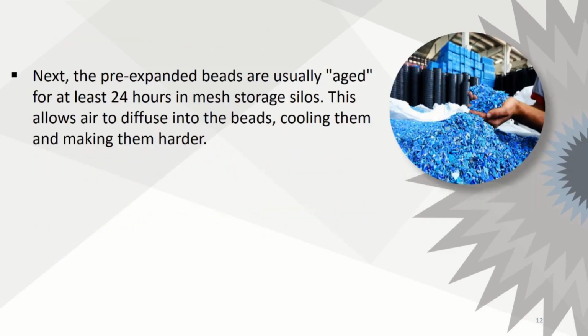Next, the pre-expanded beads are usually aged for at least 24 hours in mesh storage silos. This allows air to diffuse into the beads, cooling them and making them harder.